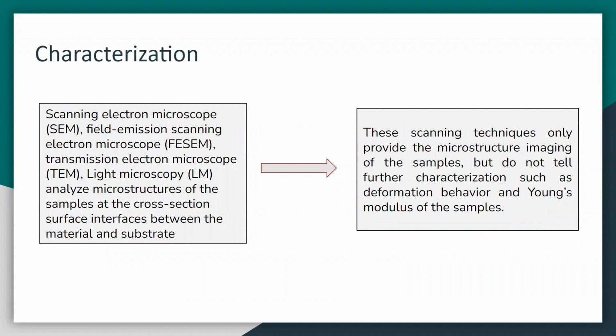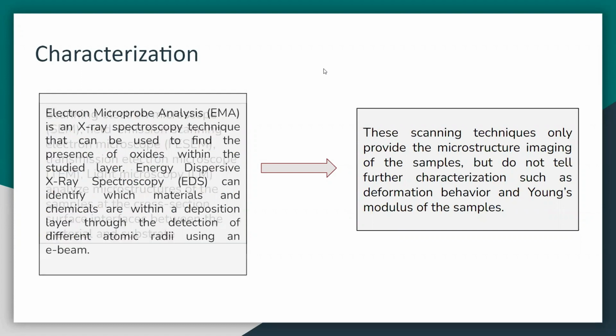Current characterization techniques to see what happens at the structure interface of these microstructures: the SEM, LM, TEM, they've been used to really analyze the microstructures at the surface interfaces between the material and substrate. And additional X-ray spectroscopy is used to see which materials and chemicals are at the deposition layer. However, these scanning techniques only provide the microstructure imaging. They don't tell further characterization such as deformation behavior and Young's modulus of the samples. And this all falls under mechanical properties and characterization.